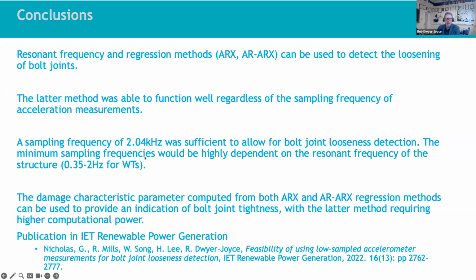The minimum sampling frequencies are dependent on the resonant frequency of the structure, and typically, as I said, around about 0.3 to 2 hertz for wind turbines. The most successful algorithm was the auto regression methods, and these can be used to provide an indication of bolt tightness, with the latter method requiring higher computational power. So I'll stop there. This is really Gary's work, but if you want to read more about it, that paper there contains the full details of what he did.